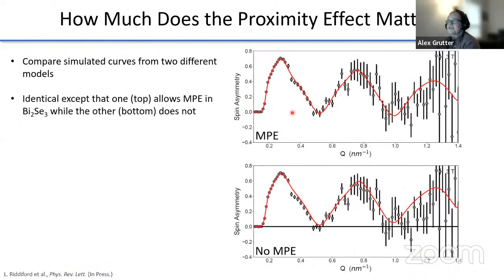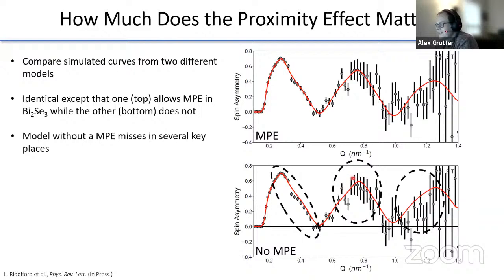So how can we understand where this idea that there's a magnetic proximity effect is coming from in the neutron reflectometry data? Because the transport data says that there probably isn't a real signal associated with a proximity effect. And so what we're doing here is comparing simulated curves from two different models, one with a magnetic proximity effect and one without. And what we see is that as soon as we turn off the magnetic proximity effect, we get a shift in the spin asymmetry right here. And we get a little bit of a shift right here so that we miss regions here and here. And you might argue that this doesn't fit quite as well, but it's kind of hard to say. But anyway, turning off the magnetic proximity effect causes the neutron reflectometry fit to miss in several key places.